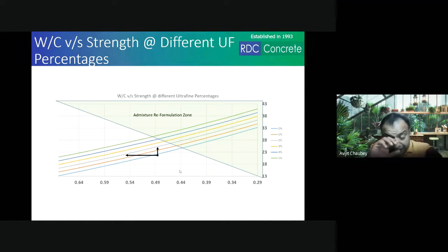Now, one more thing that happens with ultrafine minerals is, let us say you did a water cement ratio of 0.44 and you got a strength of 24 MPa, as per this graph. Now, if you want to use the same water cement ratio, 0.44, and you want to increase the strength, what you do is you incorporate, let us say, 4% of ultrafine. You will definitely get higher strength provided you do admixture reformulation.